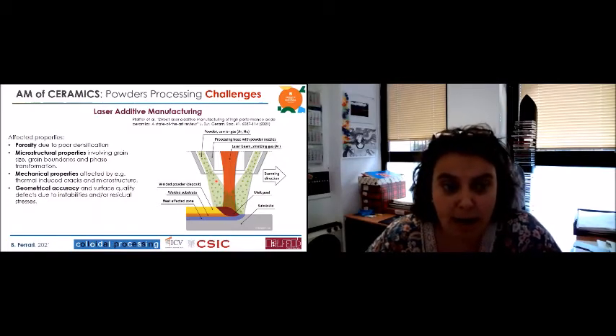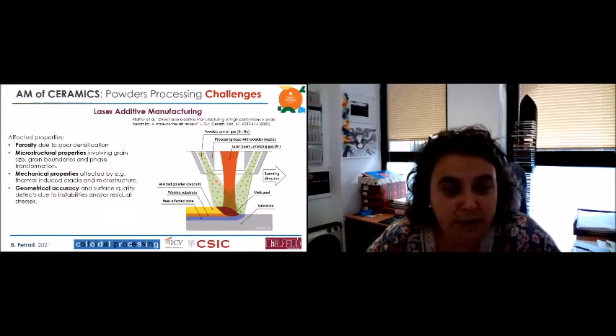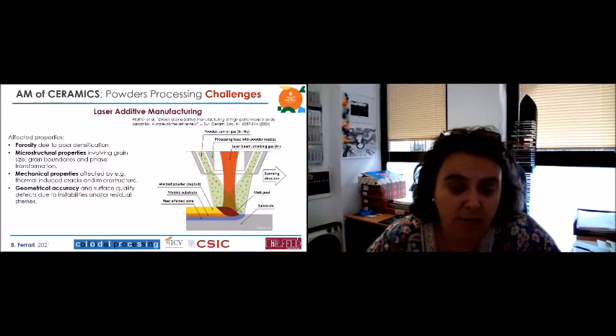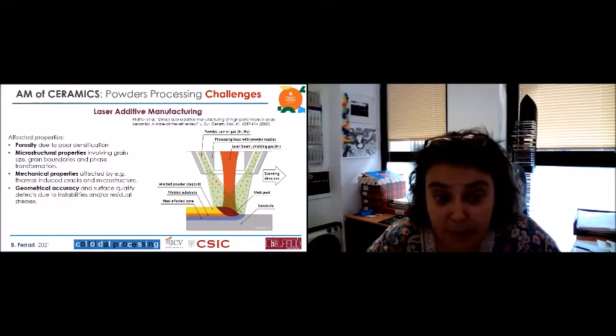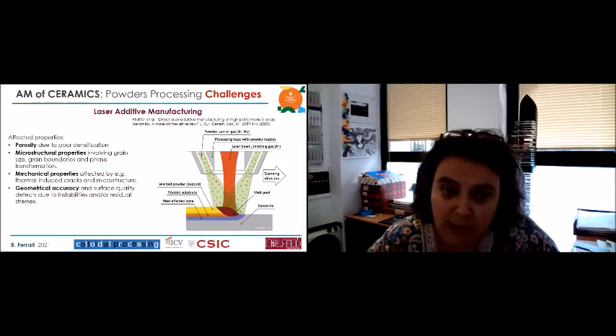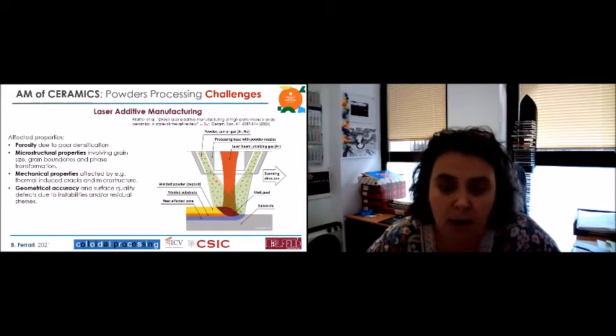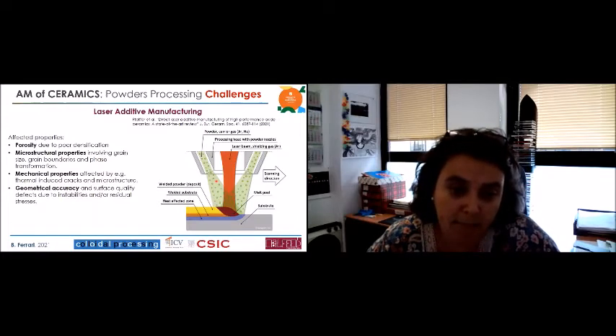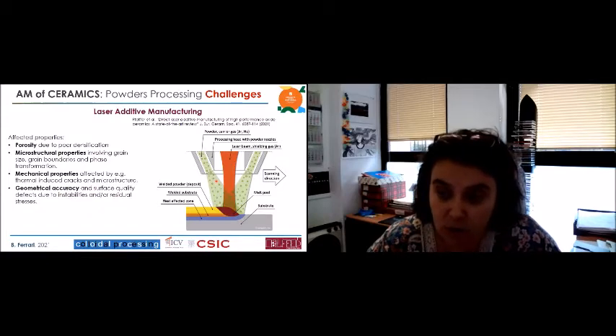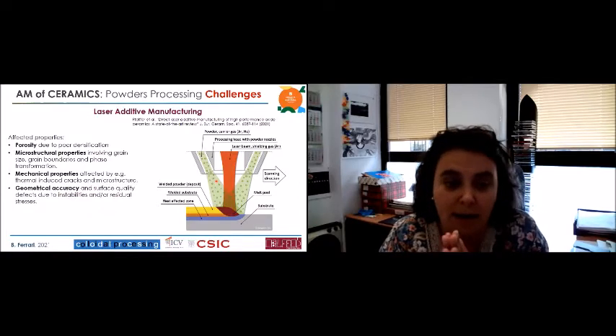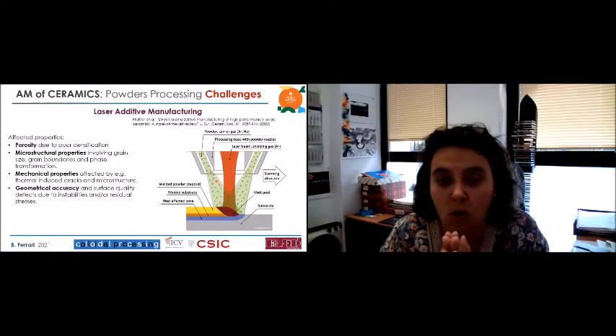that gives you some problems also, which we have to solve at this moment: the porosity is very poor, and you cannot densify very well. You can have different kinds of problems with the microstructure, because you are playing with grain size, grain boundaries, and phase transformation at the same time, and also in a non-conventional way, applying a very energetic focused light, right? And you are also changing the mechanical properties of your sintered body, and you can produce cracks in the microstructure. And also, at the end, you have the problem of residual stresses developing from this thermally induced shaping process, and the surface can also be of poor quality.